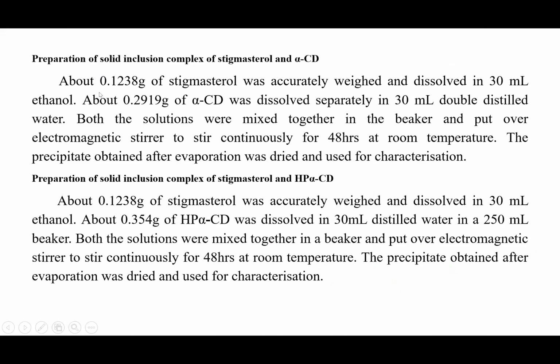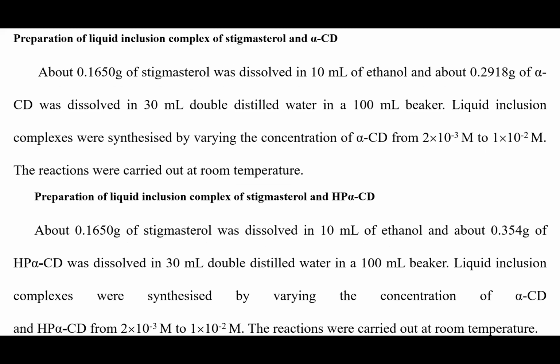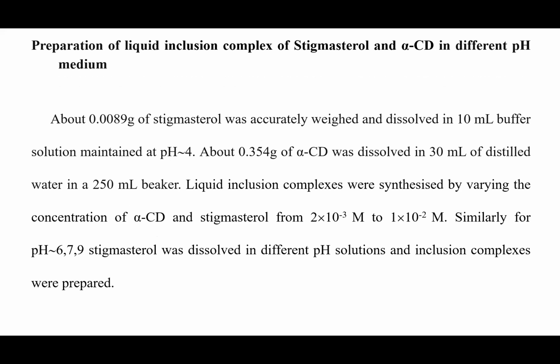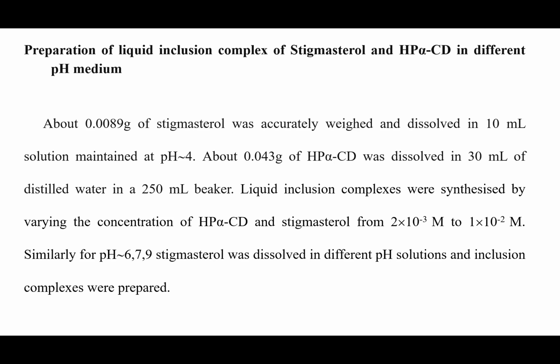That's my study. So I have prepared this inclusion complex by the evaporation method. One, I have taken a solid inclusion complex with alpha CD, and another, a solid inclusion complex with hydroxypropyl alpha CD, a derivative of alpha CD. I have also prepared liquid inclusion complexes with both the alpha CDs. So here I have varied the pH medium and prepared the complexes. I have taken pH because I want to use this complex in the medicinal field, so that we have two pH, blood pH as well as gastric pH. So I have taken the pH at 4, 6, 7 and 9 just to verify at which pH the complex is more stable. So these are the preparation methods.